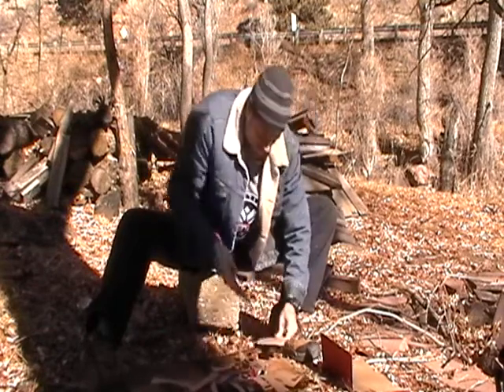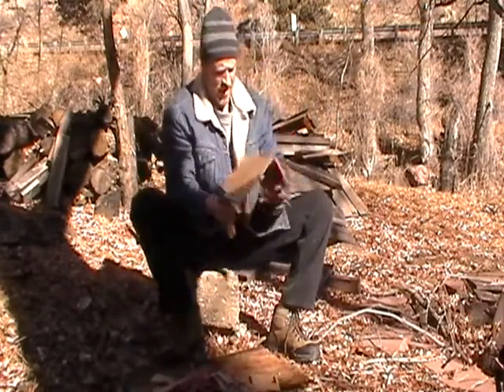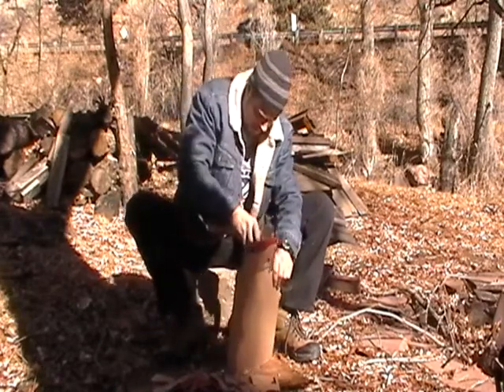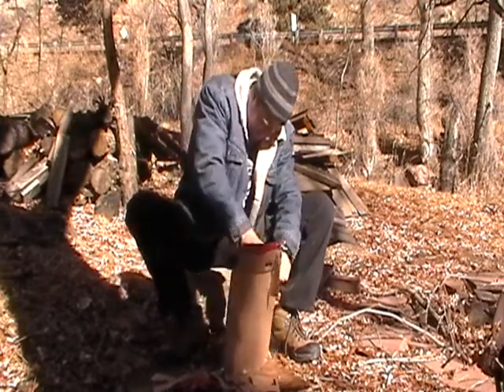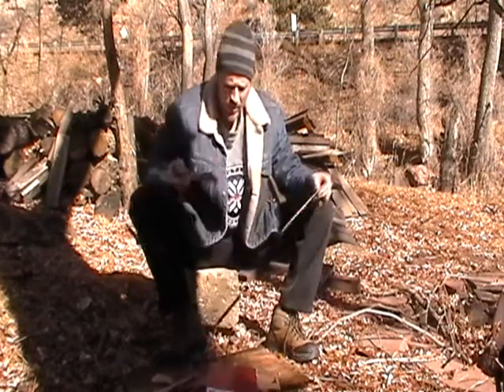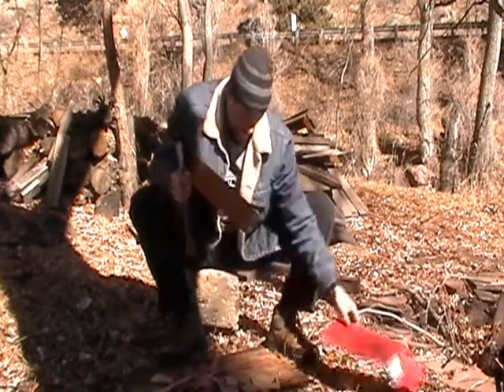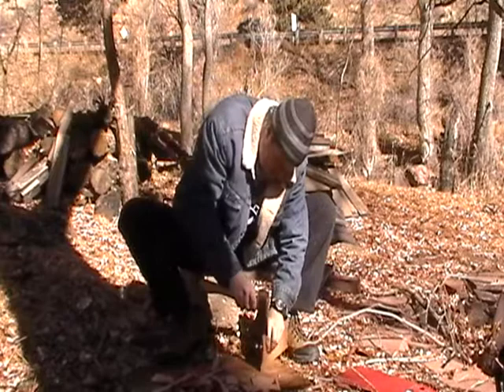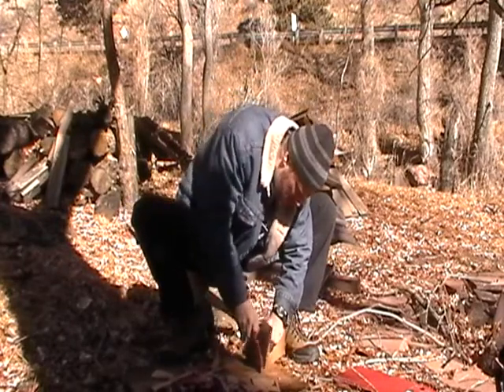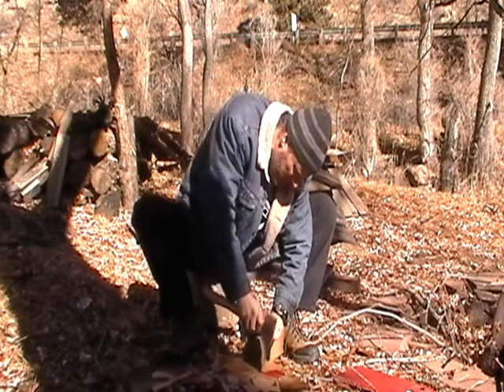The RC on these is being targeted 57. Got to claim 55 to 59, just to be real accurate. And you know, there is some variation. It's a lot harder to get the geometry or the RC on a hatchet unless you just harden it and just temper it all to one hardness. But these have a really nice differential tempering.